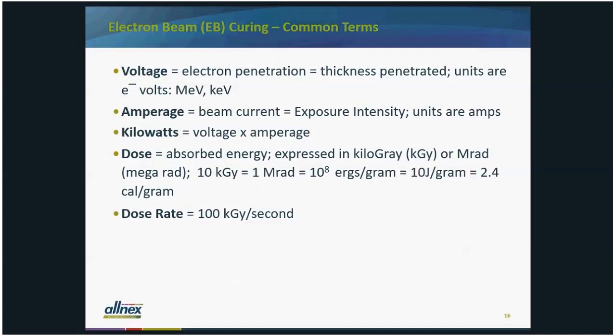Dose technically refers to the absorbed energy, not necessarily the energy that's being put out by the machine, but the energy that's absorbed by your coating and the substrate. And this is expressed in kilograys or megarads, and the relationship between those two is shown there. And finally, the dose rate, or the energy being applied to your coating with time, is in kilograys per second would be the unit. So this is just more of a reference. If you are going to get into electron beam, these are the terms that describe the energy used when using electron beam curing technology.